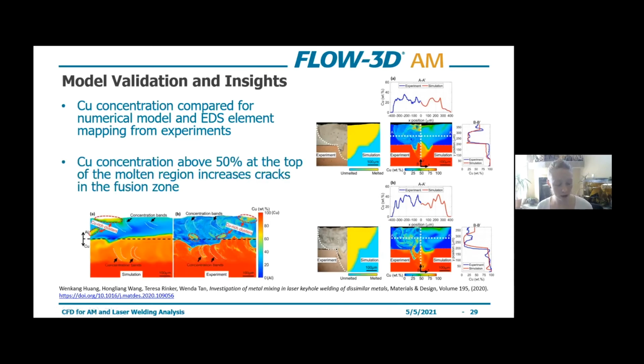And what they found was that copper concentration above 50% at the top of the molten region was leading to increased cracks in the fusion zone. So they were able to use the simulations to identify processing parameters that would lead to sufficient fusion, but not reach that 50% threshold that would lead to cracking, so that they could optimize this process of joining the 2 materials.